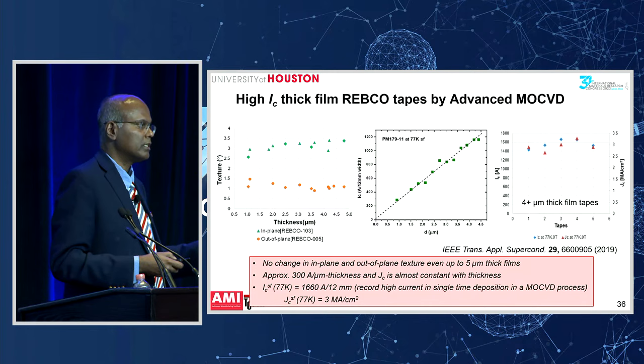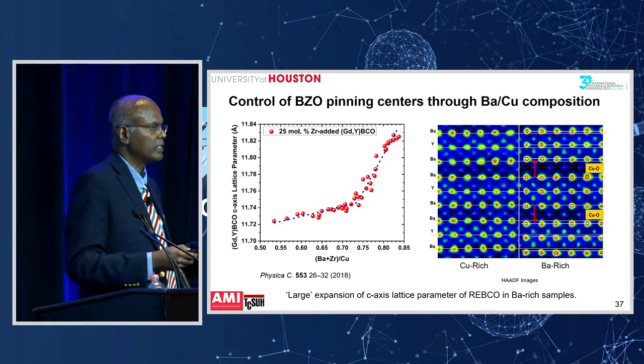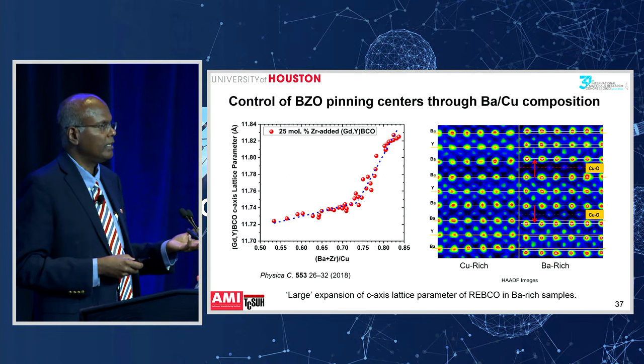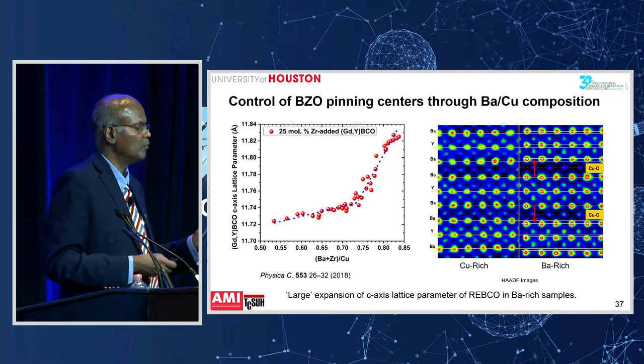Remember I told you about the barium zirconate, right? Barium zirconate or barium hafnate that we use as the self-assembled nanocolumns for the pinning centers. What we found was actually there's an opportunity to make the pinning centers a lot more effective. You can actually refine the size of the pinning centers even more by controlling the composition.